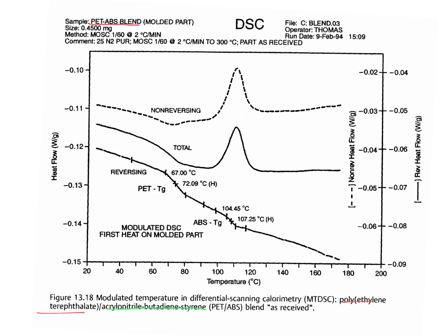So they're blending these two together, and what you see in normal DSC is what's shown here in the middle, where it goes down, then we see this increase. First off, we have to know that this is PET, and PET does this weird thing called cold crystallization, where in the amorphous state, it spontaneously crystallizes. And then we heat it up further, and that crystallinity can melt. That's off the chart of this graph. But what we're seeing in the middle here is evidence of that.